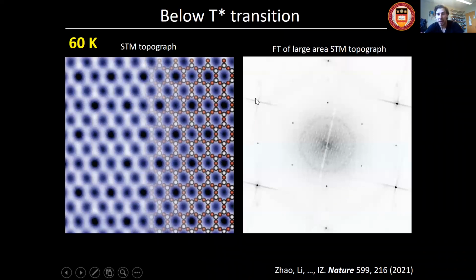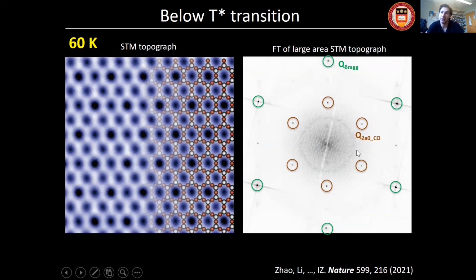So it's actually a nice periodic lattice. These are the Bragg peaks associated with the lattice that you see in the topograph. But another feature is these 6 peaks that are at half of the wave vector of the atomic Bragg peaks. So this is the 2x2 charge density wave state that was also discovered in XRD. So XRD sees this periodicity as well.